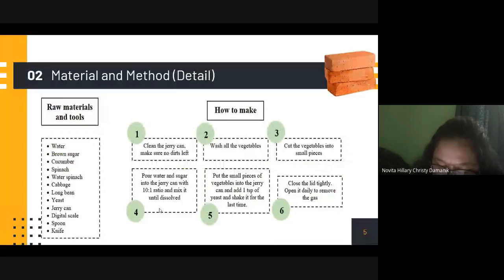Here's the detail of the preparation of the fermented vegetable, which is actually familiarly called bioenzyme. Here we need water, brown sugar, all the vegetables that I've mentioned before, yeast as the catalyst, jerrycan, digital scale, and other tools. The steps to make this bioenzyme: first clean the jerrycan, make sure no dirt's left, and then wash all the vegetables and cut the vegetables into small pieces. Pour water and sugar into the jerrycan with a 10:1 ratio and mix it until dissolved, and then put the small pieces of vegetables into the jerrycan and add 1 teaspoon of yeast and shake it for the last time. And finally, close the lid tightly, open it daily to remove the gas, and the bioenzyme should be ready in 3 months.